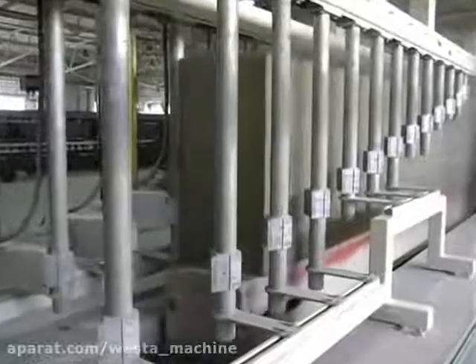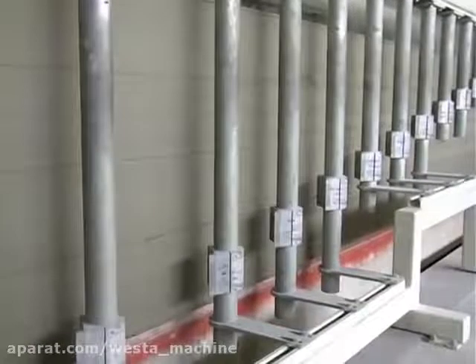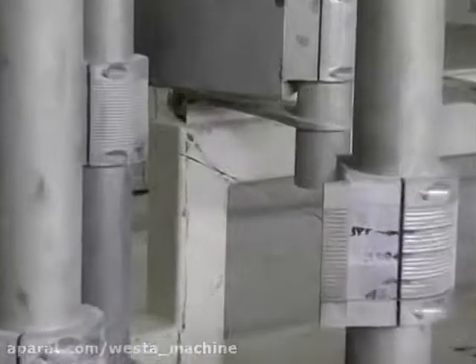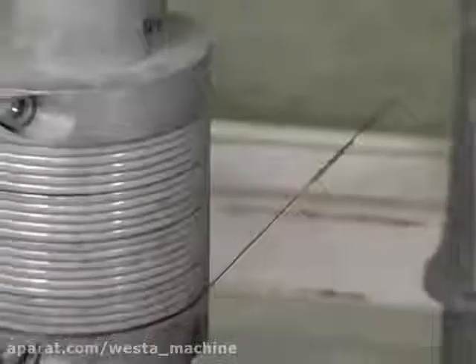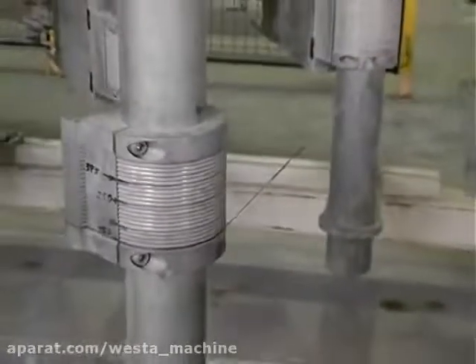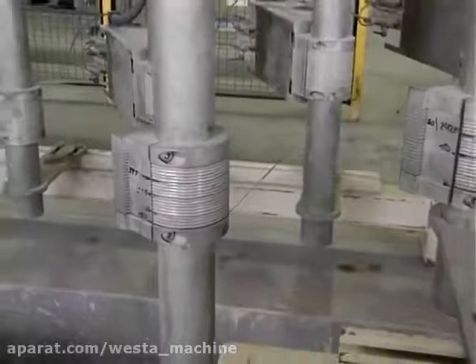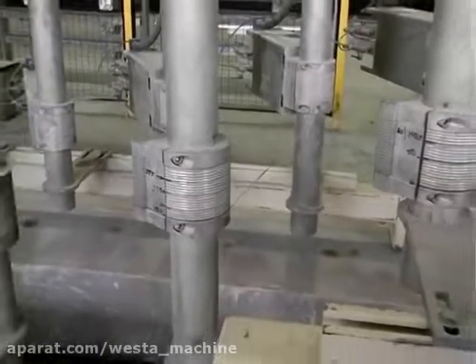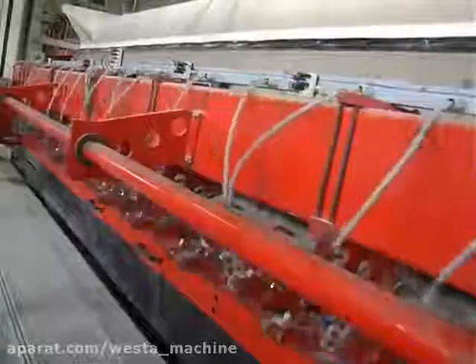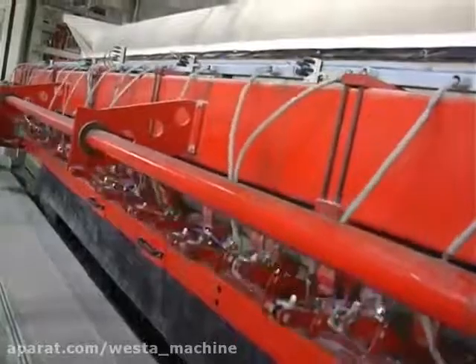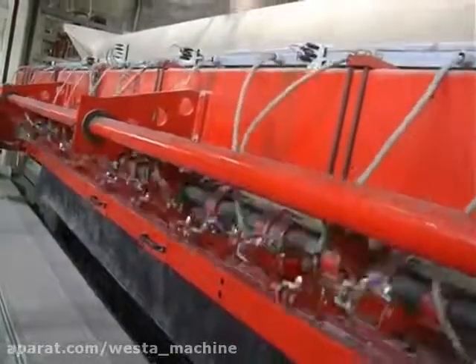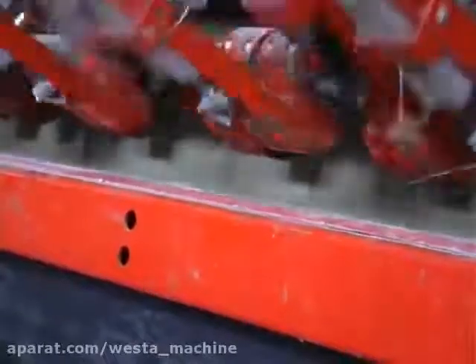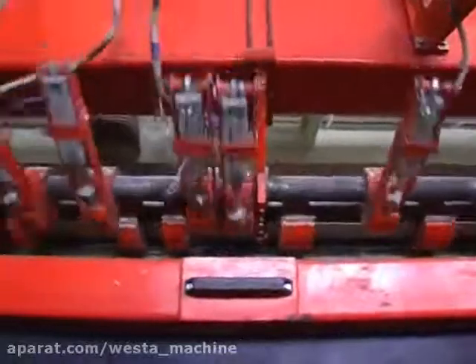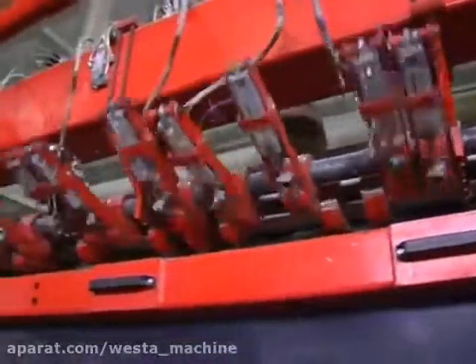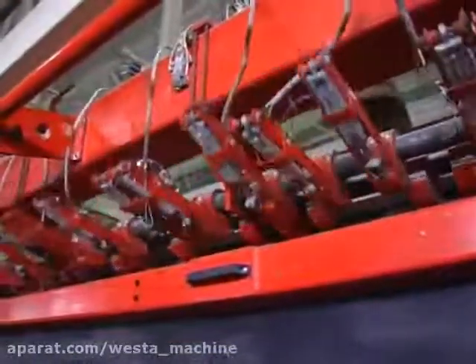The height of the block is made on the section of horizontal cutting. Pneumatically tensioned steel wires of the horizontal cutter are placed at the angle 0–60 degrees. This prevents the material from breaking off while leaving the cutting wire. Tensioned wires of the cross cutter, placed depending on the block's size, move in the opposite direction with oscillated movements. They go through the cake from up-down and cut consequently the width of the AAC block.